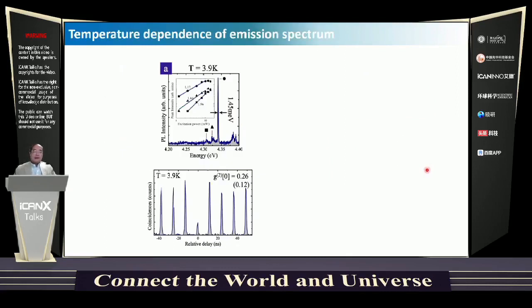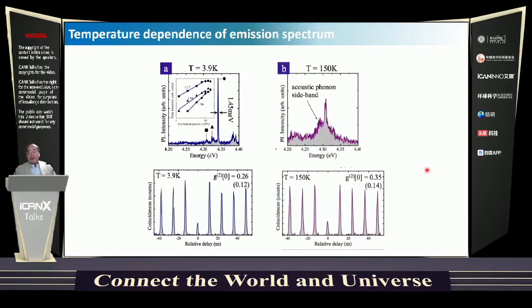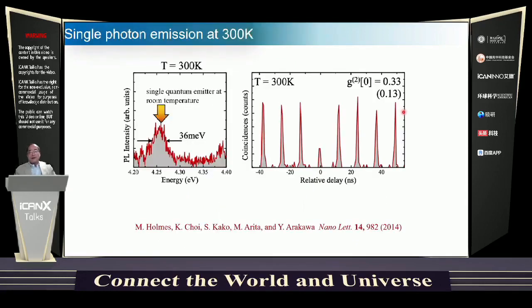Then we tried to measure the autocorrelation at various temperatures from the nanowire quantum dot structures. Here at 4 Kelvin, of course, we have single photon emission. At 150 Kelvin, we see single photon emission because anti-bunching is clearly observed. So we tried room temperature operation, and we have nice anti-bunching even at room temperature. The energy broadening is 36 milli-electron volt, which is much smaller than the biexciton binding energy, so we can see such an anti-bunching effect.